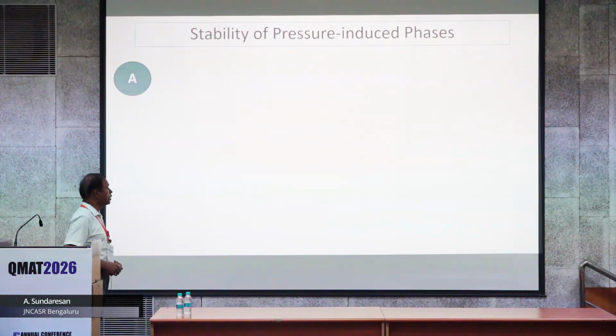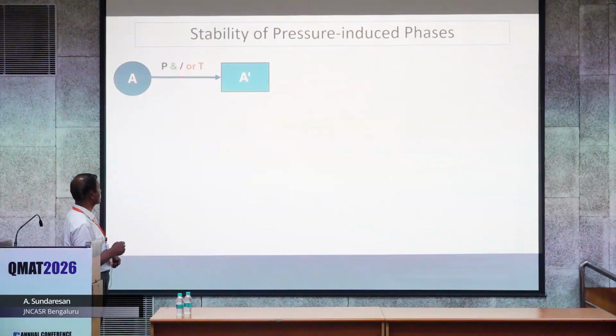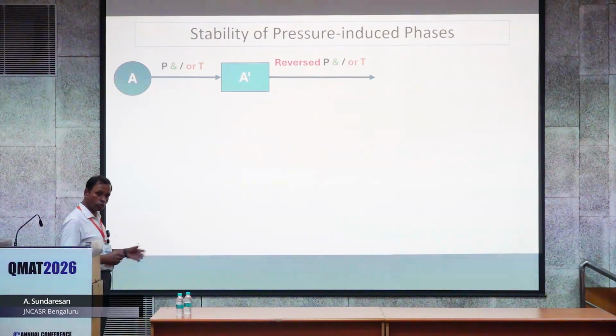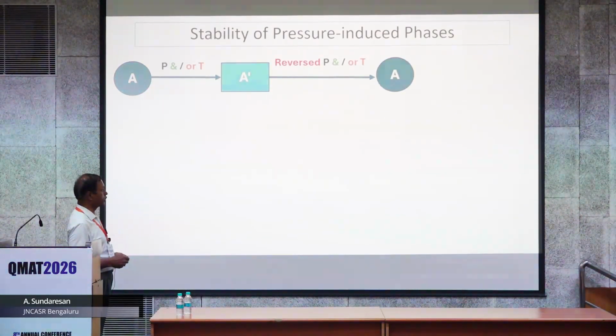Now I come to the stability aspect, which I mentioned - diamond is quite stable. So we take a material, we apply pressure or temperature, you transform this phase to A prime, another structure. Then you remove the pressure or temperature, you end up having the same material to start with, like antimony.